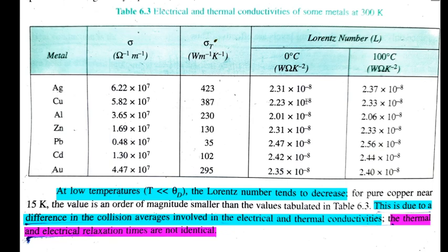But at the same time, at low temperature, the scattering cross section area of a phonon and the scattering cross section area of the electron are different, and therefore, as I highlighted here, the relaxation time change in the thermal conductivity and the electrical conductivity are not identical, and ultimately scattering theory depends on the relaxation time.